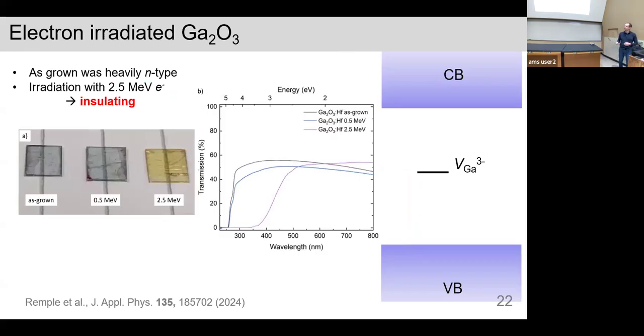So my student, Cassie Rempel, who is now at Sandia National Lab, looked at electron irradiated gallium oxide. That's another way to damage a crystal. Shoot electrons at it. The as-grown material was heavily N-type, so highly conducting. And here's the as-grown crystal. Mostly transparent, but it has a little bit of a grayish tinge to it. When we bombarded it with 0.5 MeV, it was done in France, I didn't do it myself, nothing much changed, but with 2.5 MeV, it changed into this yellowish color.